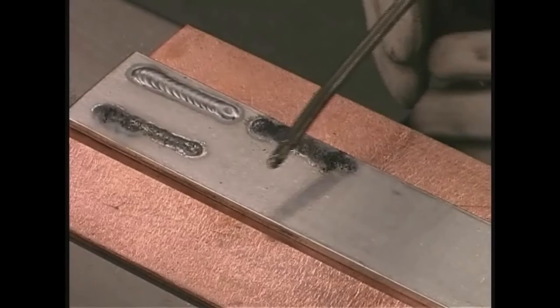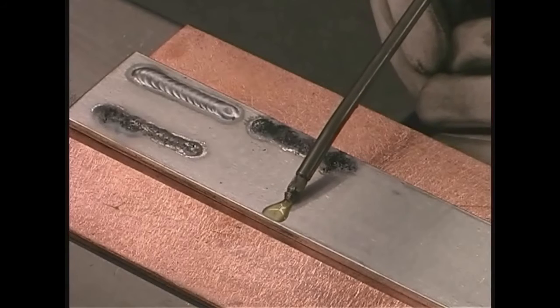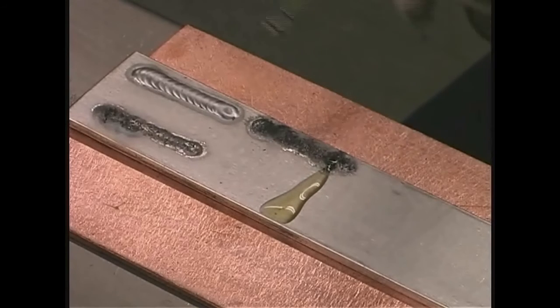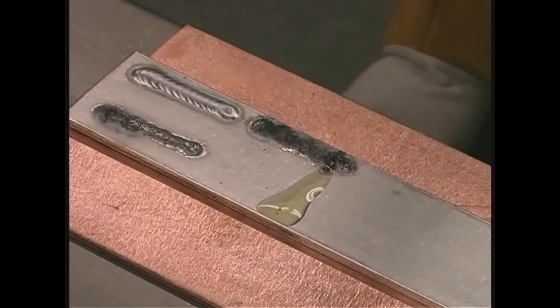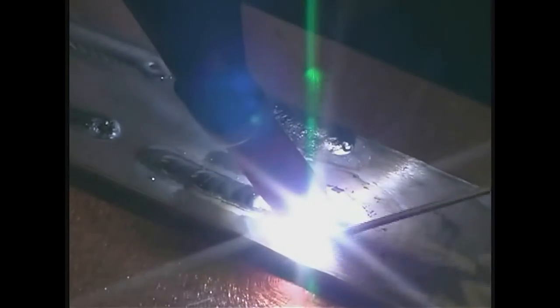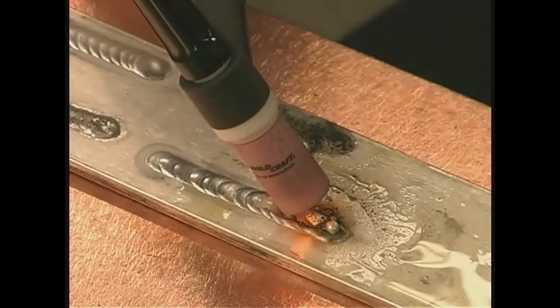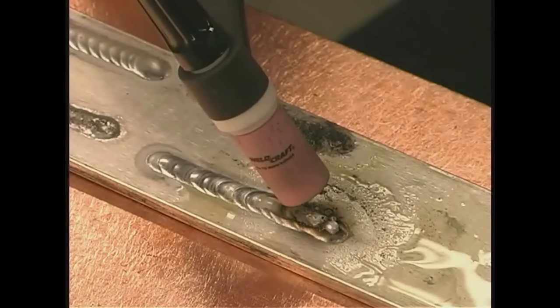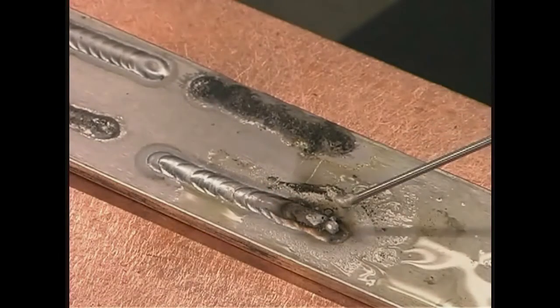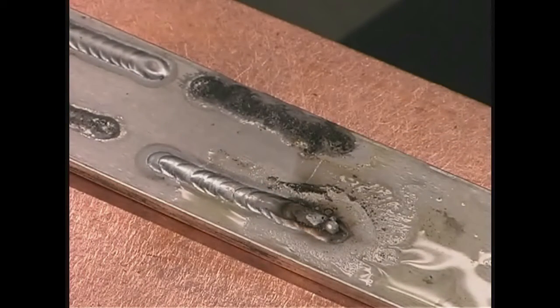I'm going to put just a thin stripe of oil on the metal, and then I'll make a weld that enters that oily area, and you'll see what happens to the weld, even though there's a full 18 cubic feet per hour of argon flowing. So here you can see what a hindrance oil is to having a TIG weld flow properly. Again, having the metal squeaky clean is essential for good TIG welding.